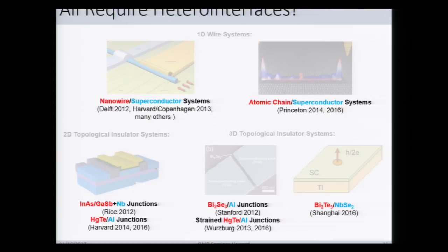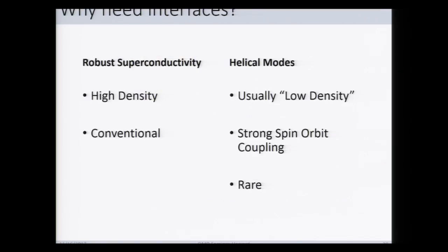Okay, but the reason that you need these interfaces is that robust superconductivity typically requires extremely high density systems, really good metals, and they're typically conventional. And then you need the helical mode. So these are low density. In the case of a topological insulator, it is literally an insulator, so zero density in the interior of the system, and they require strong spin orbit coupling, and anyway are comparatively rare.